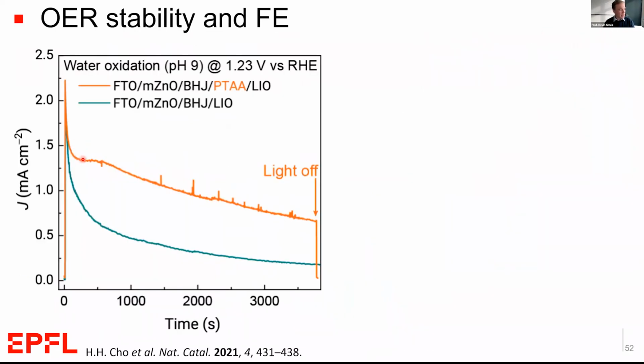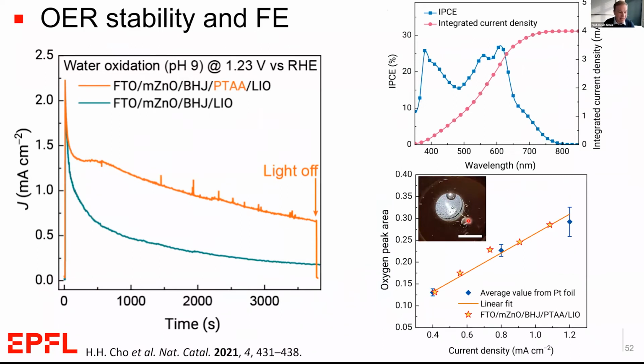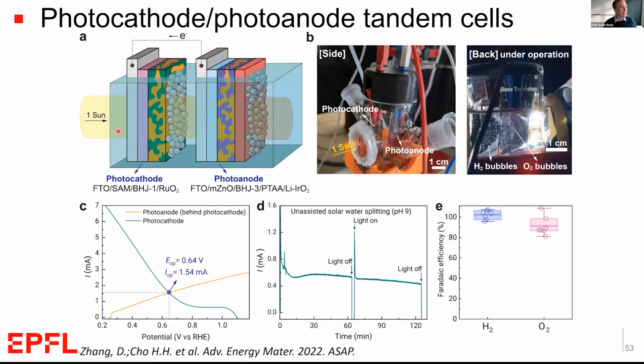The stability was improved with this PTAA layer, suggesting again that reducing the charge accumulation using a layer to extract the charges is important. And Faradaic gas chromatograph measurements showed that oxygen was being produced at a Faradaic efficiency of 100%. So we are able to take then for the first time and combine our bulk heterojunction photocathode and our bulk heterojunction photoanode into an overall device that exhibited water splitting without any applied bias. So we just shine the light on it and we get spontaneous splitting and production of hydrogen and oxygen that we can measure with the GC.